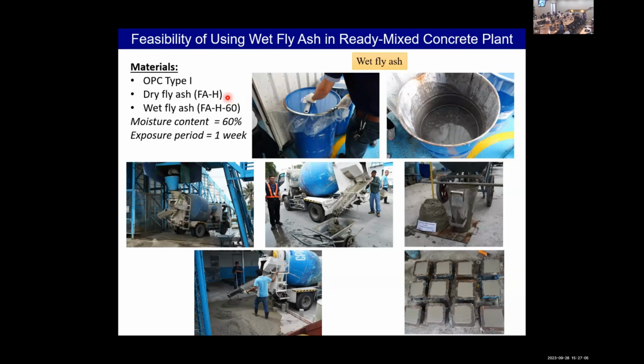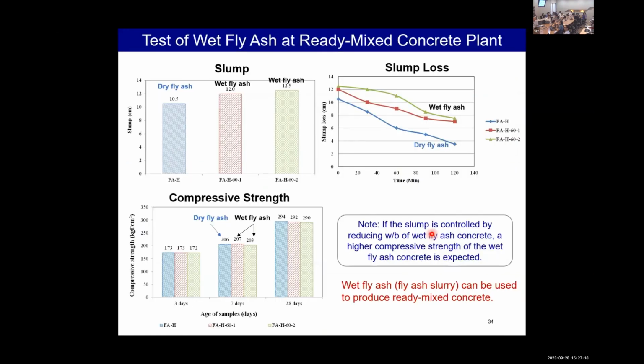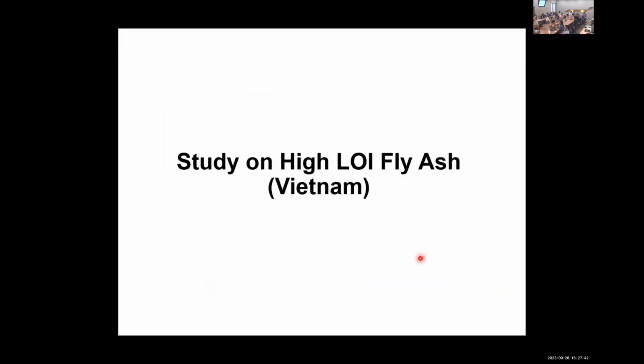For the wet fly ash preparation, in this case, we prepared it in slurry form with a moisture content of 60%. And testing at the ready-mix concrete plant, we checked slump and compressive strength, and the results show that the wet fly ash has higher slump than the dry fly ash. The slump loss is also better, and it gets equivalent compressive strength to the dry fly ash. So we can conclude that wet fly ash or fly ash slurry can be used to produce ready-mix concrete.